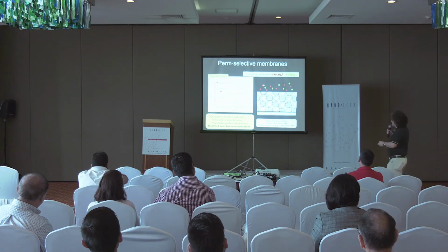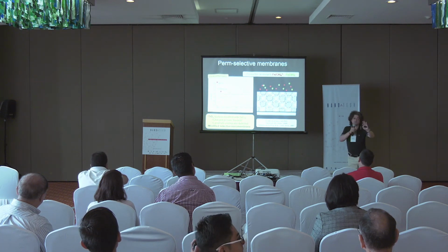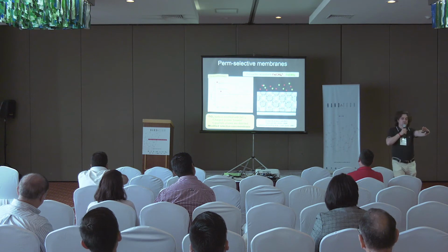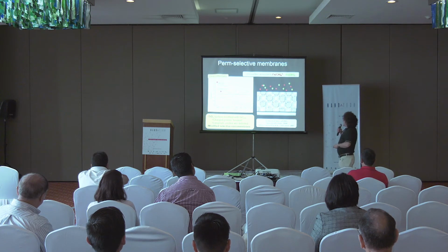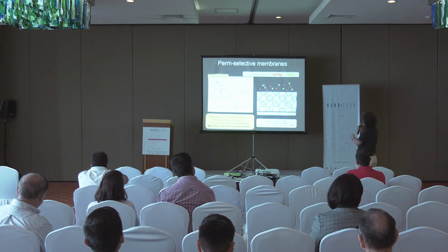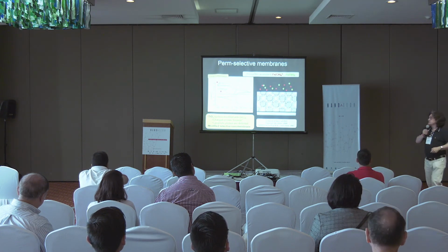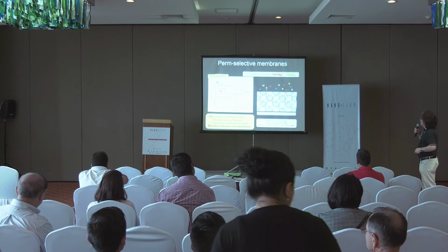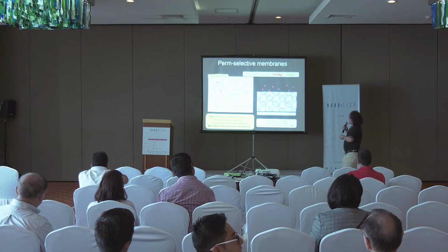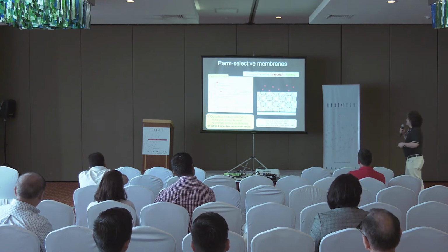Now we made the same experiment, and we see that no signal is obtained. So we put here a steric hindrance to a charged molecule. We now have hydrophilic pores, and the molecule cannot go in. But when we use this other probe, ferrocene dimethanol, which is slightly hydrophobic, this molecule can go inside. So by just changing the molecules dangling from the pores, we can separate these molecules, detect them very easily, and get these ones out. So this is interesting for molecule sorting.